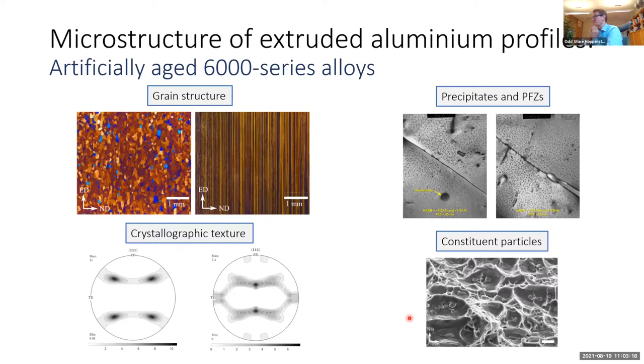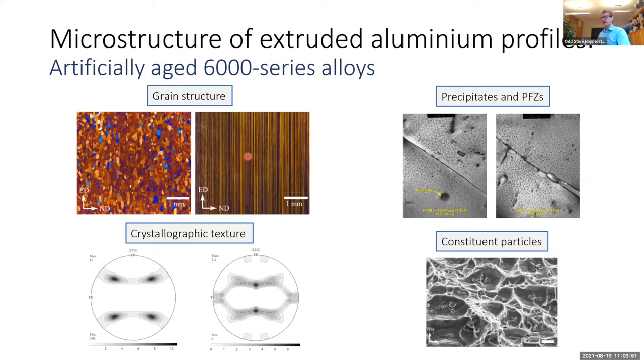After extrusion the profiles can have typically two different grain structures: either a recrystallized grain structure with equiaxed or slightly elongated grains in the extrusion direction, or a fibrous, non-recrystallized grain structure where the grains are heavily elongated and pancake-shaped. These two grain structures come with completely different crystallographic textures — the recrystallized grain structure leads to a recrystallization texture while the fibrous grain structure leads to a deformation texture — resulting in substantial and different anisotropies in the materials.